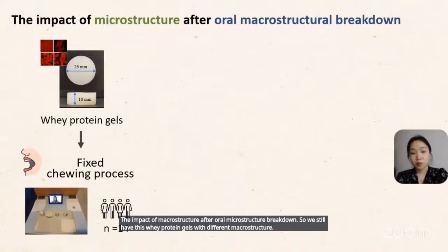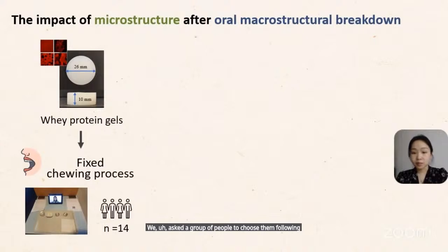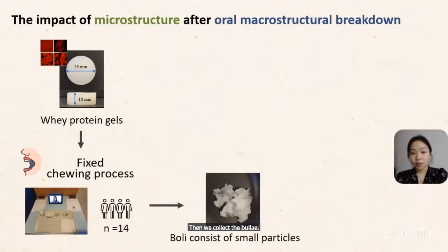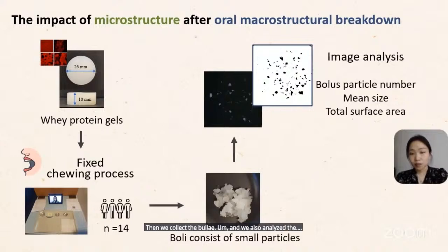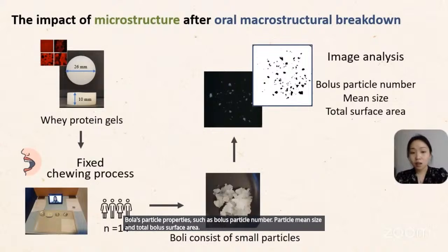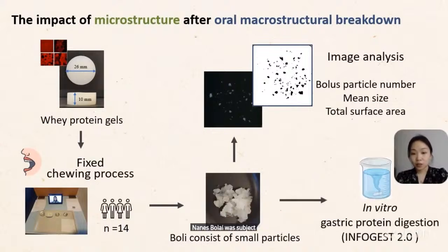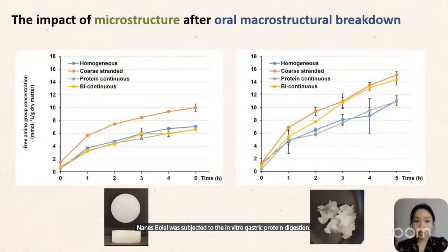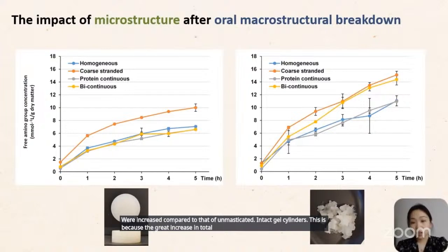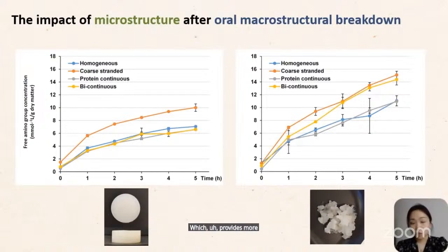We asked a group of people to chew them following a fixed chewing process. Then we collected the bolus, and we also analyzed the bolus particle properties, such as bolus particle number, particle mean size, and total bolus surface area. Then these boli were subjected to in vitro gastric protein digestion. After mastication, both the free amino group concentration and the digestion rate were increased compared to that of unmasticated intact gel cylinders. This is because of the great increase in total surface area, which provides more spots for pepsins to do protein hydrolysis.